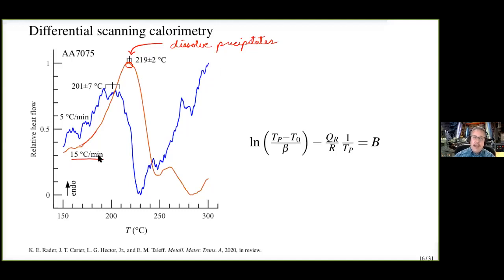If we're heating fast, we tend to overshoot the temperature at which the precipitates would like to dissolve. So we actually find the peak at a higher temperature than when we heat at a slower rate. Here at 1/3 the rate, we get the peak here. Of course, the data are a bit noisier here at the slow rate. But we see that this peak temperature shifts from here to here. And that shift is able to be analyzed. We can analyze it to think about an activation energy for that process that causes the peak.